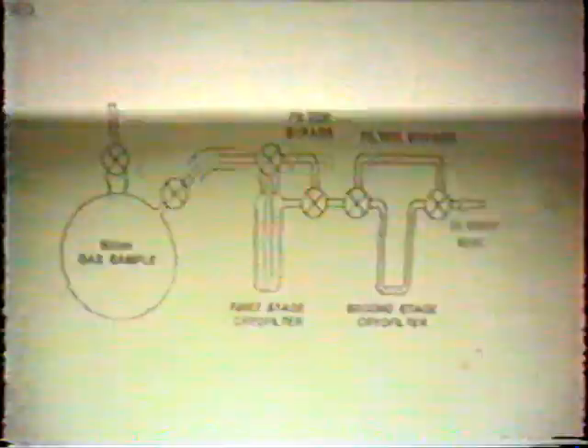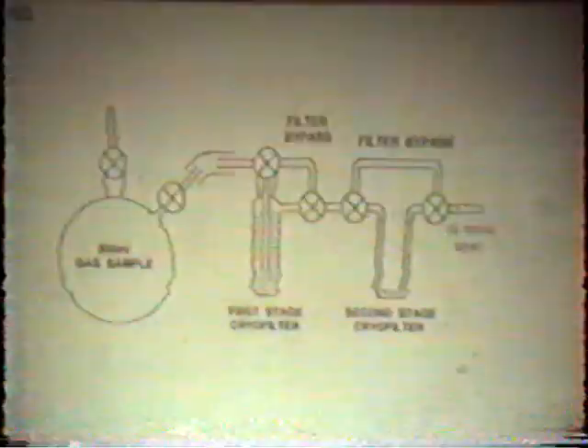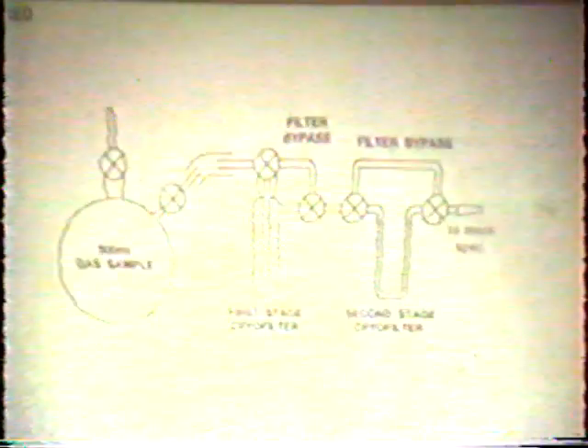Okay, the gas samples that we collected at China Lake, California, we had to ship to Texas because our mass spec could not analyze for helium. It would only go down to mass 10, so that's why we collaborated with the University of Texas. And when they got the gas sample, they connected it to a cryofilter because it's very difficult to analyze for small traces of helium, mass 4, in the presence of large amounts of deuterium, which is also mass 4. There's a slight difference, but not much.